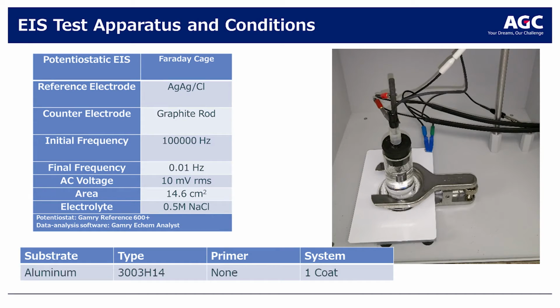And here they looked at a 0.5 molar solution of sodium chloride. They're looking at aluminum here. When you start to look at steel, it gets a little more complicated. Steel is going to show corrosion more than that. We are looking at that in the lab now, and that's kind of like what's the best method we can come up with that's going to test the top coat on steel. So it's a little more complicated than just slapping the paint on there.